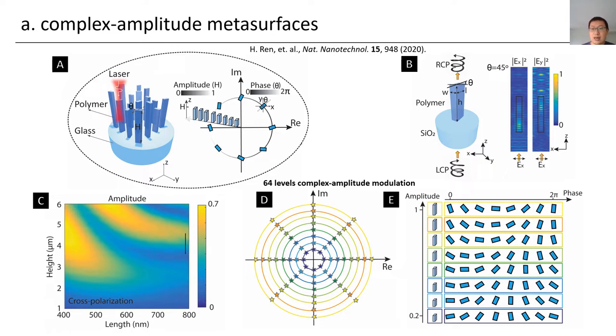For instance, this is an example in the simulation where we have this nanopillar to be anisotropic and oriented at 45 degrees with respect to the incident polarization angle EX. So if we shine on this EX polarization, we can see that the outgoing transmitted light is barely small. However, if we switch the output to this EY polarization, you can check that the major component of the transmitted light becomes the EY polarization. So switching from the EX polarization to the EY polarization means that our fabricated or to-be-fabricated 3D meta-atom has a strong birefringent property, which can allow us to achieve the geometric phase, where we can use this in-plane rotation angle to control the outgoing phase distribution.